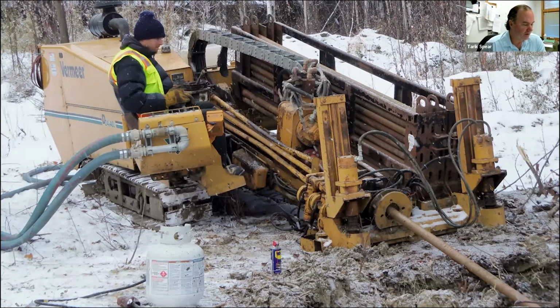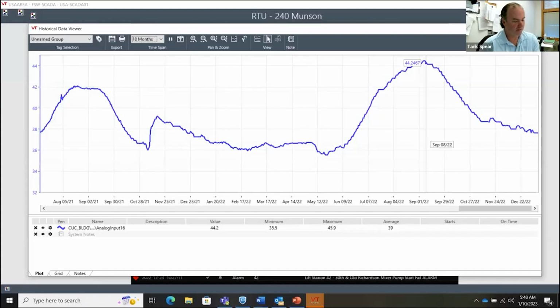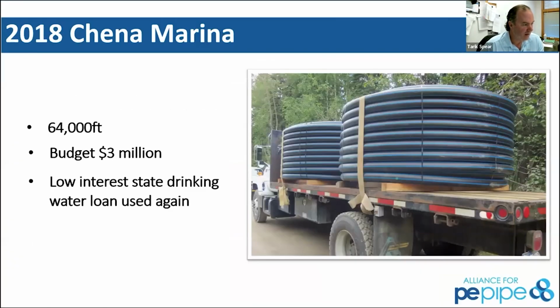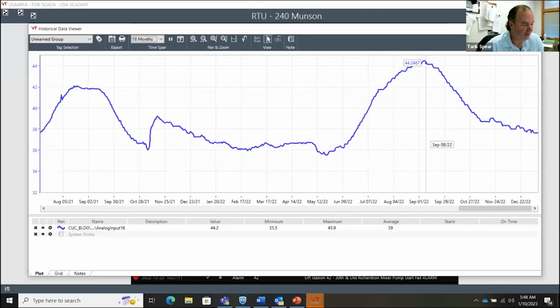This is a SCADA view of one of our circ loops, and it shows the thermal heat loss throughout a year. We spend about $640,000 in steam heat every year from a power plant to keep some of our outer loops at 36 to 38 degrees. Take December 23rd: the ground temperature is still dropping, and the water temperature is dropping, even though this main is circulated at 100 GPM. It's about 64,000 feet of main, and it flatlines around March or April, and then we have what's called the spring push, around May. Every year when the surface starts to thaw, the frost runs away from it and goes deeper, so we see a drop in our water temperatures right around May. Then it starts increasing again June, July, August, until it starts dropping again in late September.